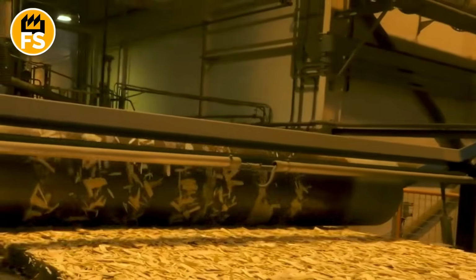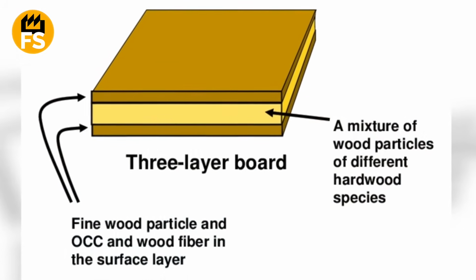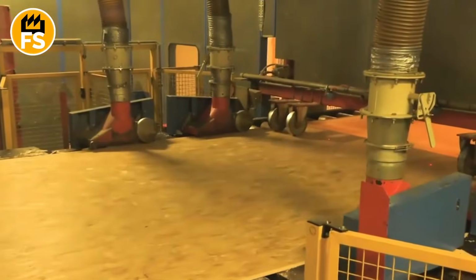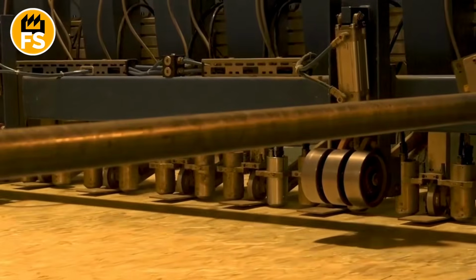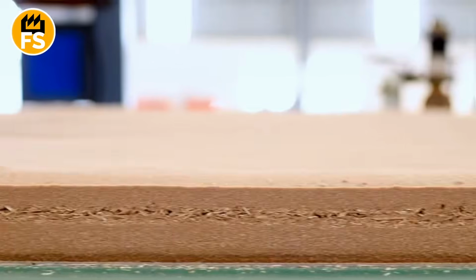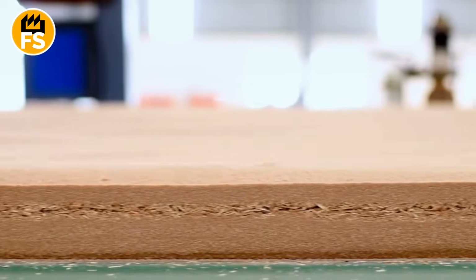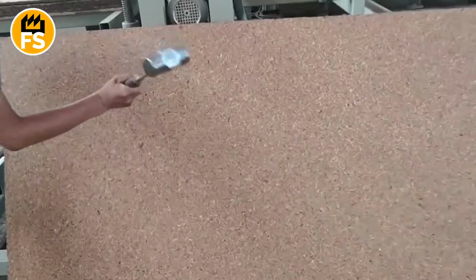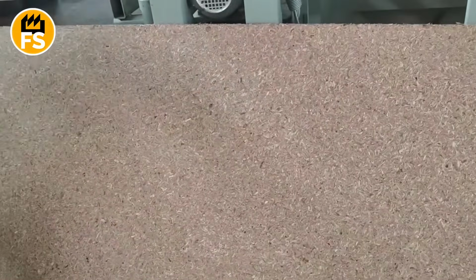Here the strands are laid out perpendicularly, that is, crosswise. And finally, the top layer is again laid out lengthwise. As a result, we get a thick, fluffy, 3-layer pie, where the fibers in each layer are perpendicular to the fibers in the adjacent one. It is this cross structure, which imitates the strength of plywood, that is the secret that makes oriented strand board incredibly strong in bending and resistant to deformation.